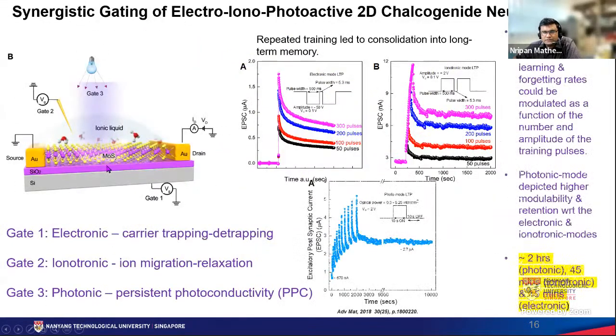In this particular work, we worked with a 2D material which is photoactive, so we technically can use a photonic gate as well. We had a bottom gate control, we had the top gate ionic liquid control, and since the ionic liquid is transparent, we can also do optical control. The reason we went for optical control was because the amount of charge carriers you can induce in any semiconductor by gate voltage is ultimately limited by the breakdown strength of the dielectric you use, either the breakdown of the SiO2 or the splitting of the ions in the ionic liquid, etc.